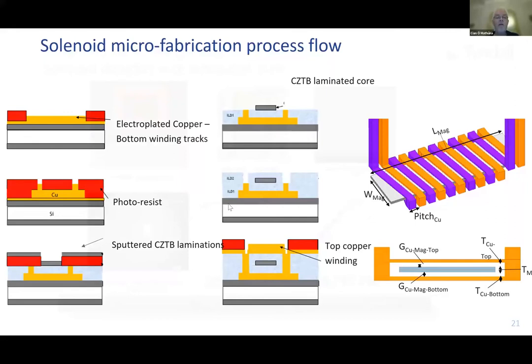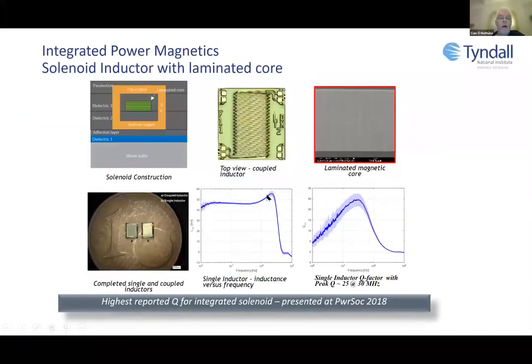The important information here is that we wanted to be able to operate this inductor above 100 megahertz, so 10 to the 8. So we have a 50 nanohenry inductor operating up above 100 megahertz. And the other thing that was important, I mentioned the Q. We were able to get a peak Q of 25 in the region of 20 to 30 megahertz. And at the time, in 2018, at the Taiwan PowerSoC, that was the highest reported Q for these integrated magnetics.